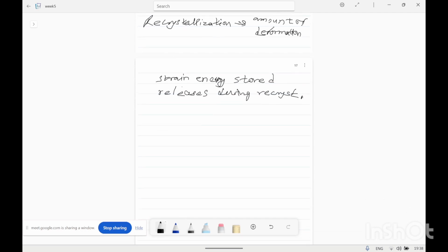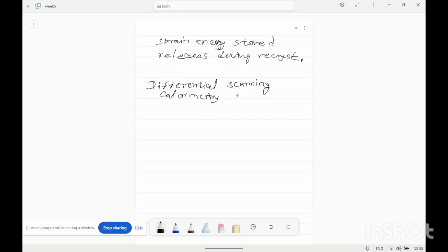So if we want to compare two samples, one which is cold worked, second is annealed. So how can we distinguish between two samples if we do not know their working processing history? So one method is differential scanning calorimetry. So in DSC, the heat flow in the material is analyzed. So this is the heat flow. This is positive. This is high.